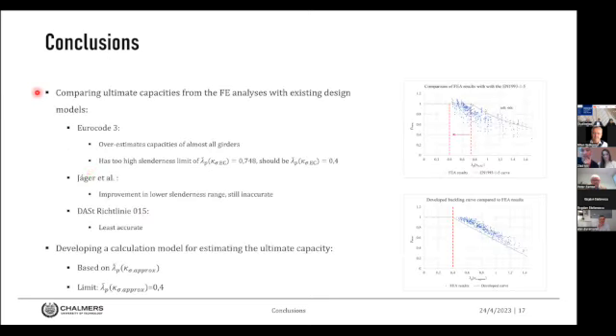And lastly, comparing the ultimate moment capacities from the finite element analysis with existing design models. Firstly, the Eurocode resulted in overestimations for almost all studied girders, and this was concluded to be the result of the too high slenderness limit suggested of 0.748, where 0.4 would be more reasonable. The model of Jaeger et al. had some improvement in the lower slenderness range, but was still inaccurate. And lastly, the DASt-Richtlinie was the least accurate model.